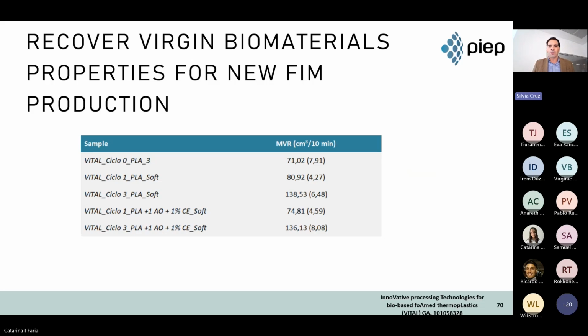We went to the extruder to validate that, and in the end, I would say that we expected a bit more improvement. It was not what we got. What we got was only a slight improvement on the lower degradation of the material. At least when we measured the MVR, we saw that with the reprocessing cycles, the material is getting less viscous and more fluid, and there is still some degradation.